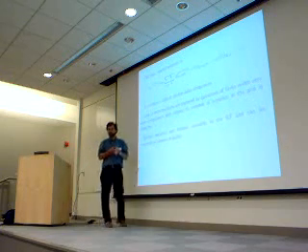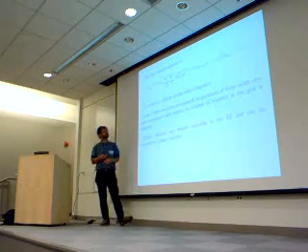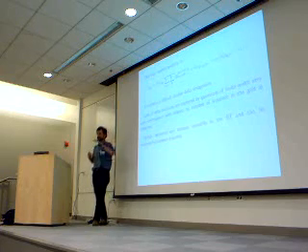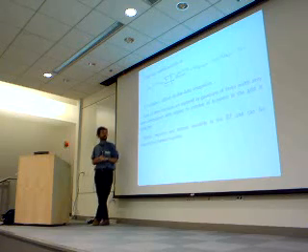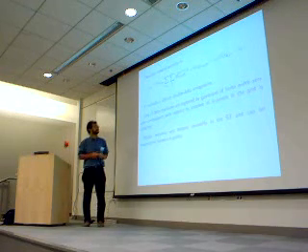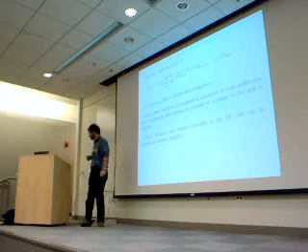This grid, which is very dense for normal purposes, is not dense enough to integrate accurately the double delta at such a small smearing, while at larger smearing the results level off and you have a rather regular behavior. So this is something that one has to take care of, and accurately check the convergence.